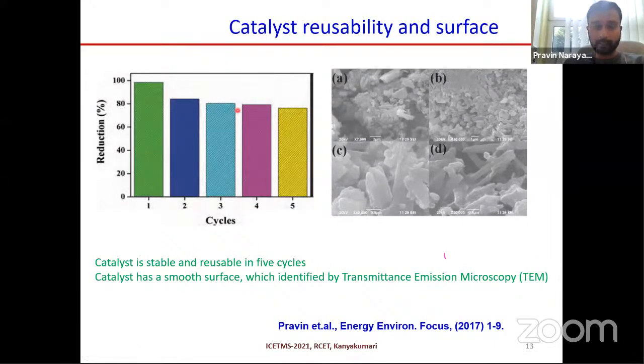efficiency of the catalyst. And this is the transmission electron microscopy of the metal complex to confirm the surface of the metal complex, because the smoothness of the surface is very important for the energy transfer process. So the size of the particles is 400 nanometer, and the surface is very smooth.